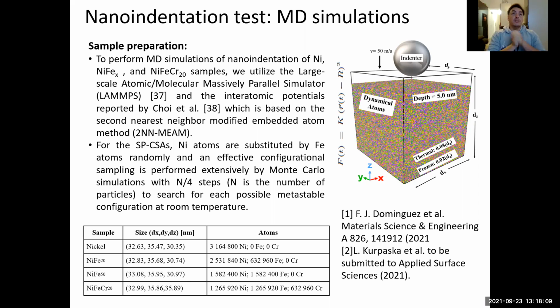But the story doesn't end there. Now we need to make sure that this sample can be compared with the SP-CSA. So how are we going to do it? We are carrying out this Monte Carlo simulation with the swapping method. So when we are doing the optimization of the sample and the swapping of the atoms, the swapping needs to satisfy some restrictions in the energy and the entropy to identify and to get the sample, which is the possible metastable configuration at room temperature. So this sample is for sure the SP-CSA, or as close as possible to the material that they develop in the laboratory. We also are sure that the atomic distribution of the sample in each direction is the same. So everything needs to be created really carefully.